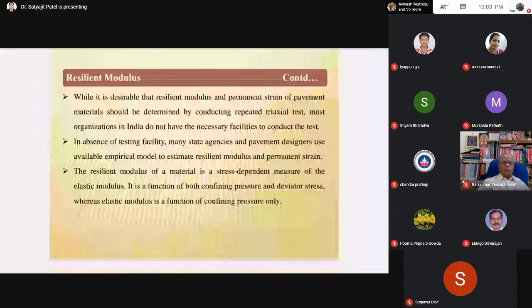The resilient modulus of a material is a stress-dependent measure of the elastic modulus. It is a function of both confining pressure and deviator stress, whereas Young's elastic modulus is a function of confining pressure only. So for a given material and a given confining pressure, Young's elastic modulus is constant. But resilient modulus depends on both sigma 3 and sigma d. With a change in deviator stress or load applied on the specimen, the resilient modulus is different. So it is not a constant quantity for a given material and a given confining pressure. This is a major difference between resilient modulus and elastic modulus.